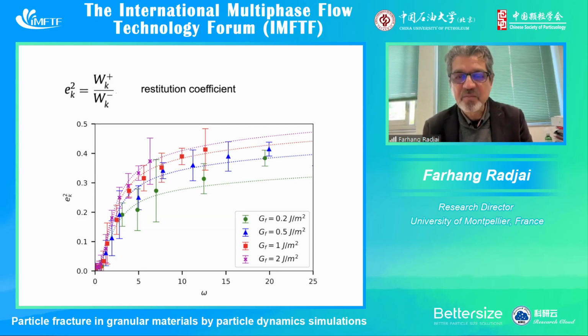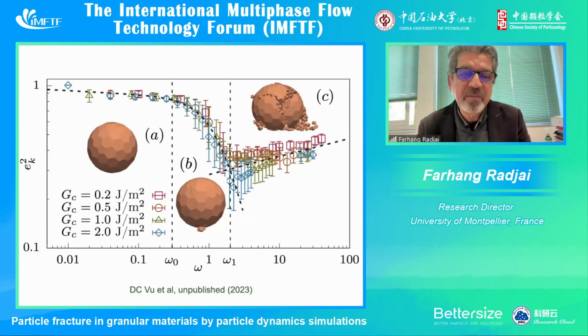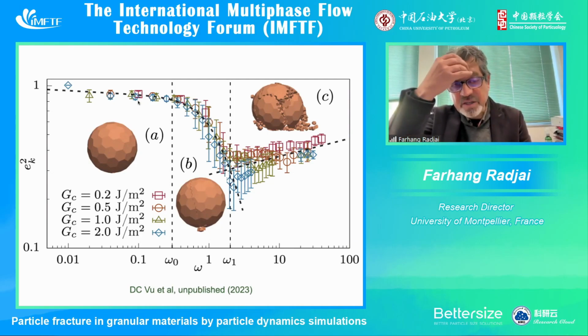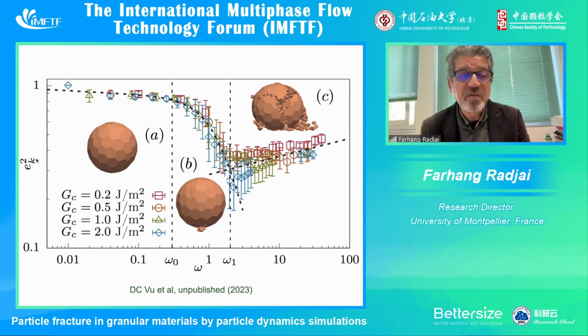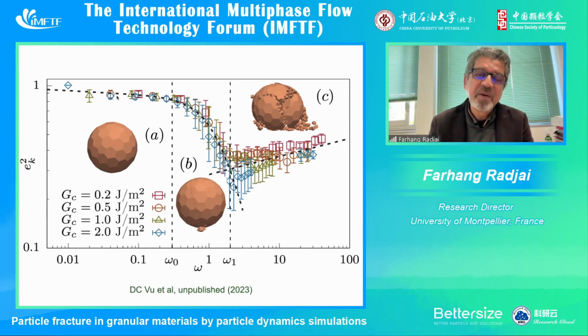But later we did more simulations using this time the molecular dynamics approach, or the smooth particle dynamics approach. We found that actually we have this more complex behavior. At low values of omega, we have elastic behavior. So we have rebound without fracture. And the restitution coefficient here is very close to 1 because we use also high restitution coefficient between fragments.